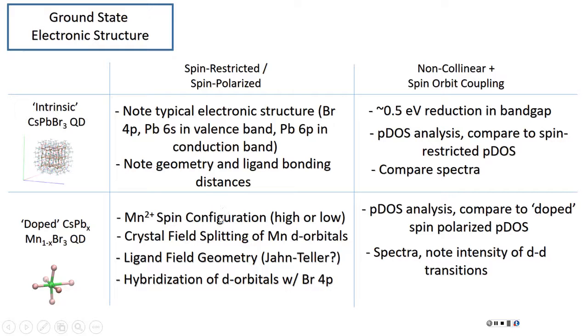And then it's kind of complicated, because we looked at the orbitals, but the orbitals aren't very straightforward to analyze just by looking at them, because you have crystal field splitting, which splits the d orbitals of the manganese ion. And then there also appears to be some distortion of the geometry, so it's not perfect octahedral. It's more like a square pyramidal structure, because this bond here is like 0.8 angstroms longer than all the other ones, and it's more bonded to a lead that's out here than it is to the manganese. So it seems like there's some sort of Jahn-Teller distortion.